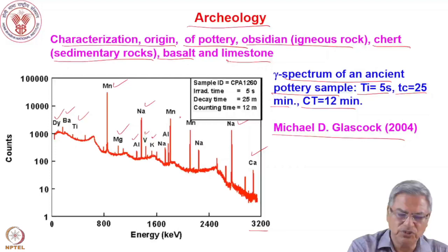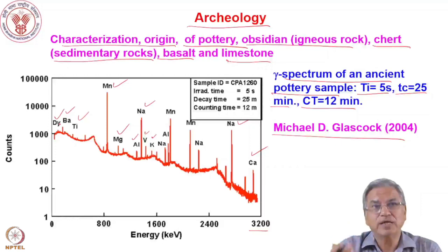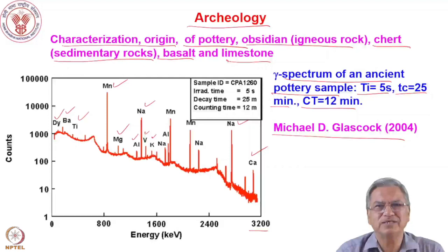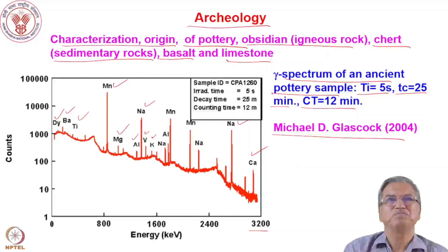The gamma spectrum from an HPGe detector covers up to 3 MeV (3000 keV). You can see a large number of elements: barium, titanium, manganese, magnesium, sodium, aluminium, vanadium, potassium, and others. One isotope may have several gamma rays — like sodium. In one spectrum from a single counting, you can analyze 8 to 10 or more elements simultaneously. That is the beauty of NAA — multiple elements can be determined from a single counting of the sample.